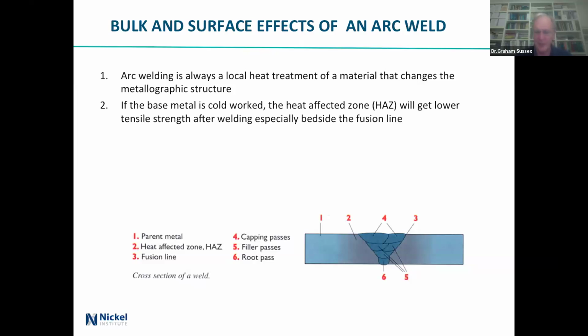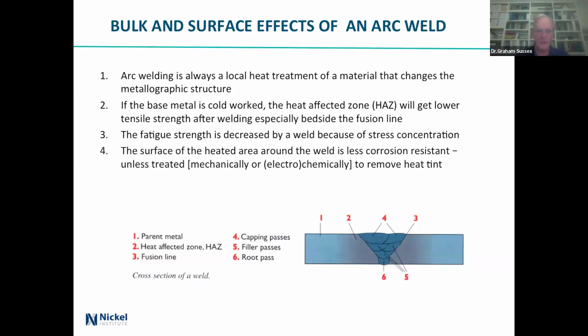Capping passes on the top, they're different. And you've got possibly problems at the fusion line, and then filler passes and the root pass. And they're all different weld structures, all different temperatures, and all you need to be thinking about what's happening, or the designer of the weld procedure. So this area around the heated thing is less corrosion resistant, the heat tint we've got, unless